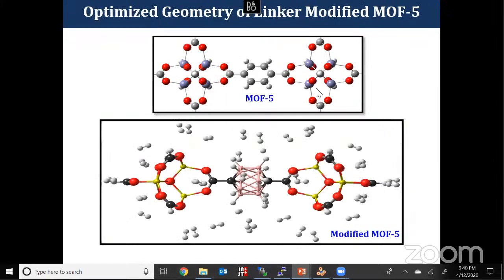This is one of the main interesting things. What I did here is replace the existing MOF5 linker with the carborane moiety. As I mentioned, it can adsorb 20 hydrogen molecules, but when we incorporate it into the MOF5 linker, this part has a repulsion, so we can't store hydrogen molecules here. But this drum part of the carborane can still hold hydrogen molecules, so it still adsorbs 10 hydrogen molecules. But the actual MOF5 adsorbs a maximum of 2 hydrogen molecules.